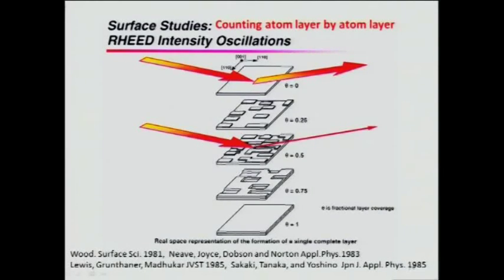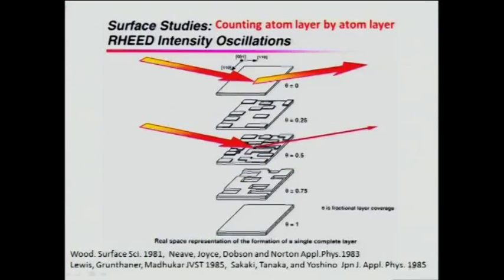And how does this happen? If you have an atomically smooth surface, the reflected beam at that spot has a very high intensity. As we grow on the surface, of course, different islands start to form on the surface at the beginning, before the islands coalesce into a complete smooth surface. The highest island density is, of course, at the 1/2 order point, where there are the most islands. And then when you get to 3/4, more and more coalesce together, forming smoother areas. Finally, a complete layer is formed. Again, this is as smooth as the beginning, so the intensity of this beam gets back to the maximum again.